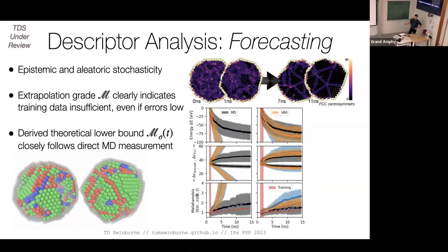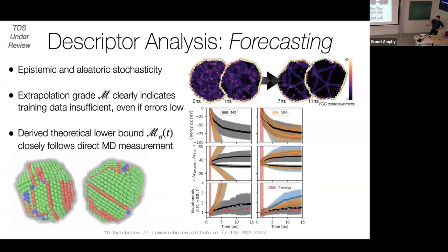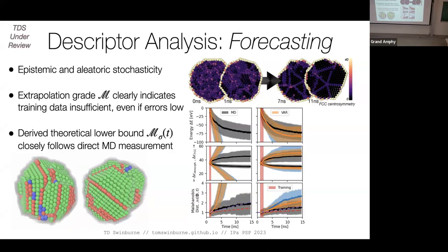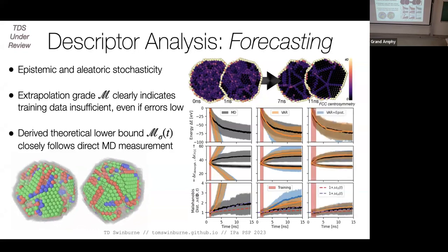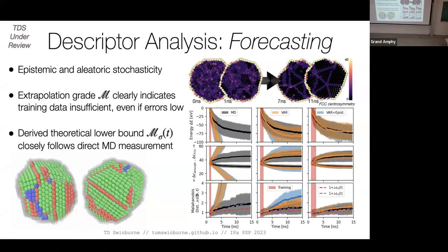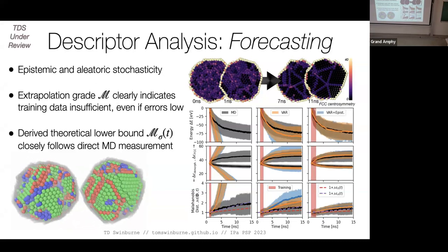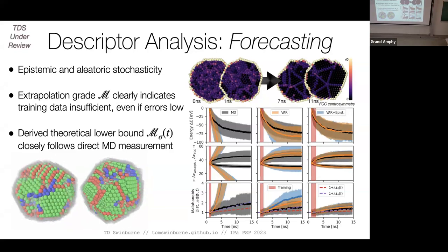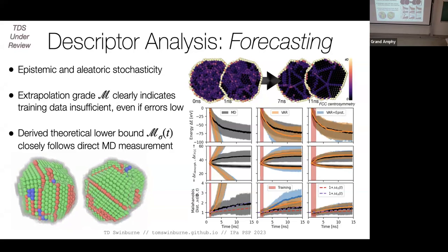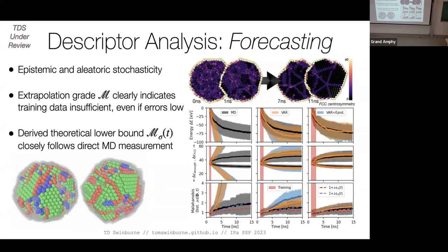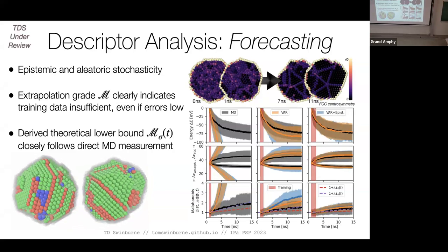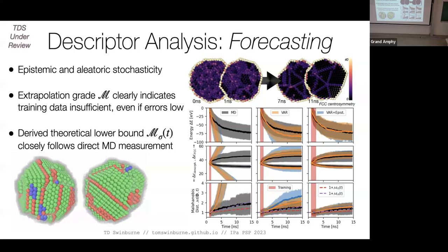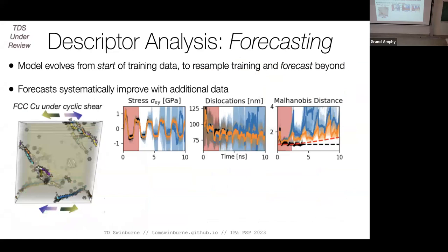When I increase training a little bit, I'm already getting better — my extrapolation grade goes much lower, and my theoretical bounds on the minimum growth very closely match the MD. With a bit more training data, I'm getting pretty much bang on the MD and the extrapolation grade remains low. I'm predicting a 50-dimensional vector, then extracting out the energy, FCC content, amorphous content, and other properties by looking forward in time. It's a fairly simple nanoparticle system, but we can look at much more complicated systems.